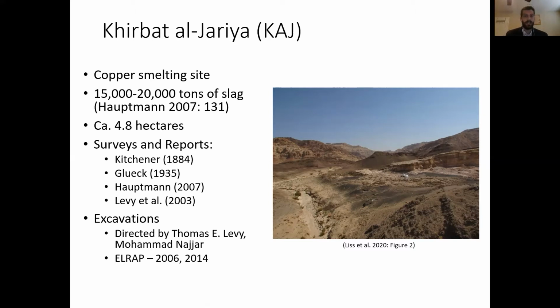It is an Iron Age copper smelting site, as you can see by the accumulations of slag on the site's surface. In the photo on the right, you can see those black heaps. Andreas Hauptmann estimated that there's roughly 15 to 20,000 tons of copper slag at the site. And between the slag and the architectural collapse, the site covers an area of about 4.8 hectares. It actually extends on both sides of the wadi. This photo just shows the eastern and more dense part of the site.